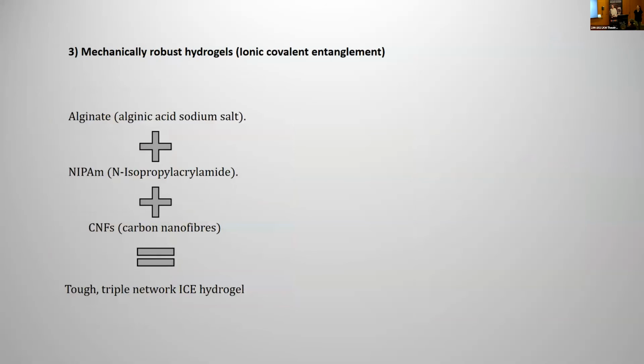It does have some uses. So the next one, I touched base on that, saying that soft robotics often want mechanically robust hydrogels. So when you think of hydrogel materials, they're usually 99% water, 95% water, which doesn't make for the most strong materials. So you have to have a few techniques to make them stronger or more robust.